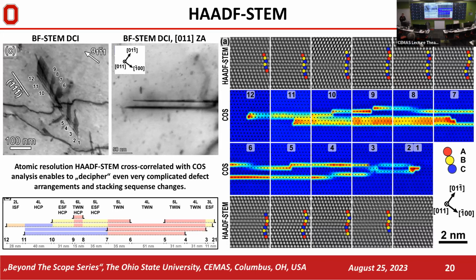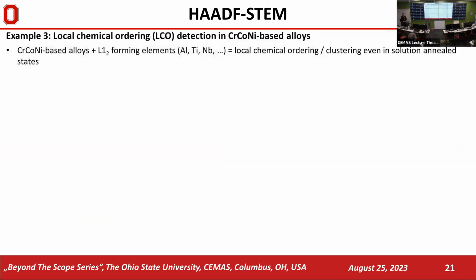this cross-correlated approach nowadays can help us to decipher even very complicated defect arrangements and stacking sequence changes in these alloys, with low stacking fault energy or with precipitates, where complicated things are happening in terms of plasticity and deformation mechanisms. Here you can see with atomic resolution preciseness, you can resolve where you have transitions between intrinsic and extrinsic stacking faults, HCP stacking, or twin sequences. So this is a huge advantage.